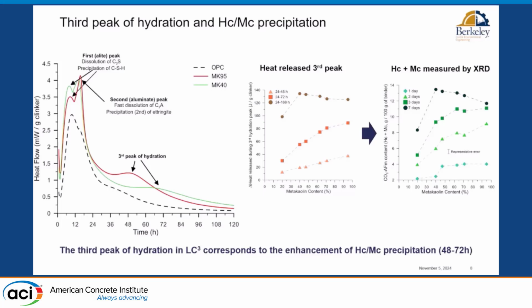We start from here, H1, H2, third peak of hydration here. When we compare the heat release over that peak, it correlates very well with the amount of carboaluminate that we can quantify by X-ray diffraction. So basically now we can assign a feature that we can observe in the calorimetry curves of an LC3 cement with the precipitation of hemi and monocarboaluminate. And we can start seeing some particularities of the process.